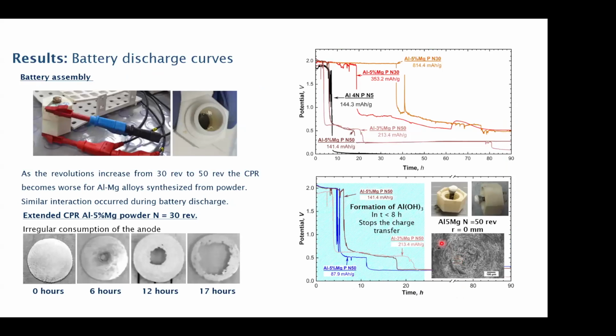So unfortunately, the powder consolidated was a little bit less stable, but we do see that the center is probably one of our biggest challenges because it corrodes a little bit faster, and that probably makes these discharge curves not so steady as we would like. But improving the dispersion and the grain refinement in the center, in terms of using the HPT process for this kind of batteries, is the challenge, but we are working on solving this problem.